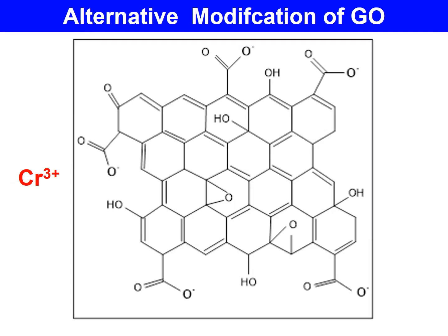Alternatively, we can add carboxylic acids by adjusting the pH. We're going to dissociate the COOH to make it COO-, and then chromium 3+ will be attracted, or any molecular species that's plus, it will be attracted. So if we modify graphene, we can either add positive functionality or negative functionality.